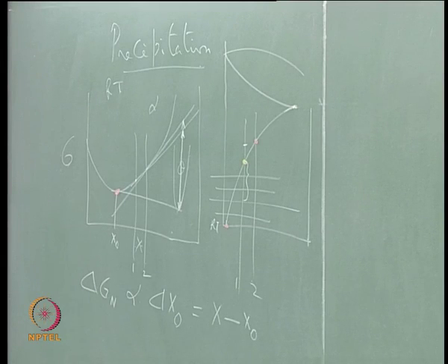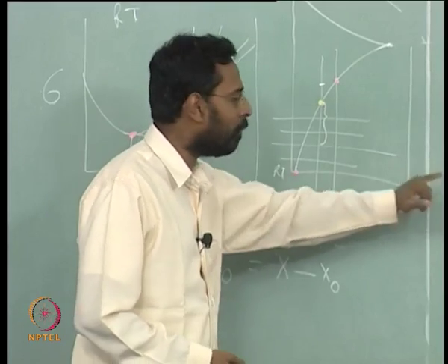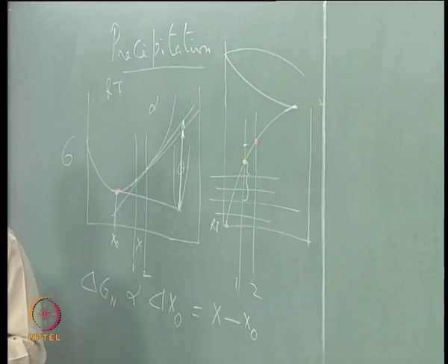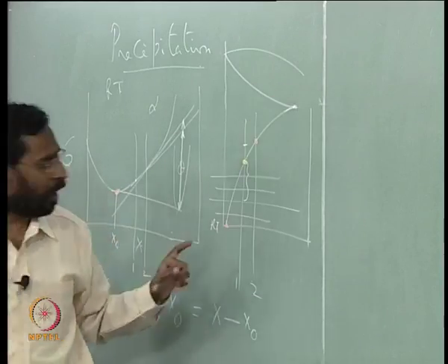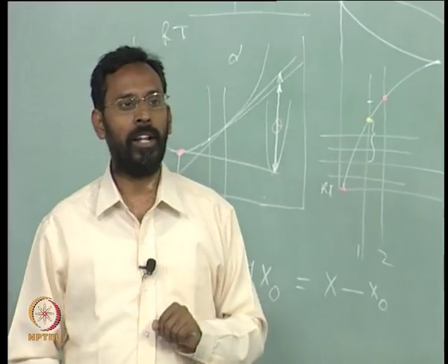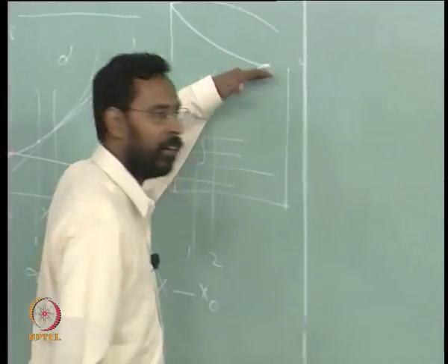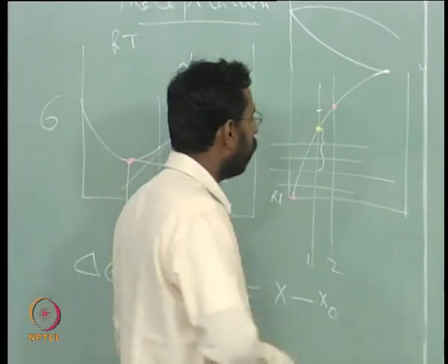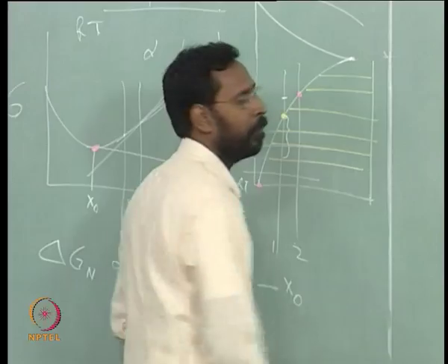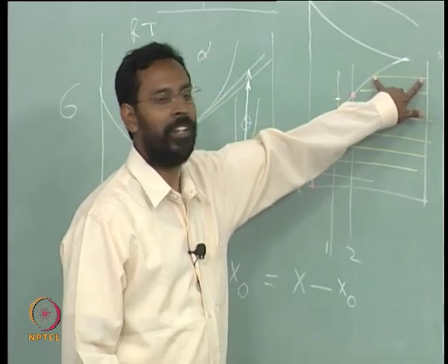Theta has to dissolve. Why does theta have to dissolve? Because the solvus line, if you carefully observe, shows the solubility of copper in alpha aluminum is increasing with increasing temperature. That is what this line tells you. Because the solubility is increasing, and at each temperature if I calculate the weight fraction of the second phase using the lever rule, it keeps on decreasing, because this length is decreasing, isn't it? And from that you can see from the lever rule that the amount of theta is decreasing,